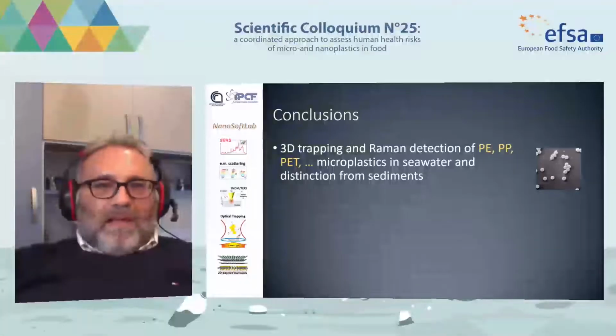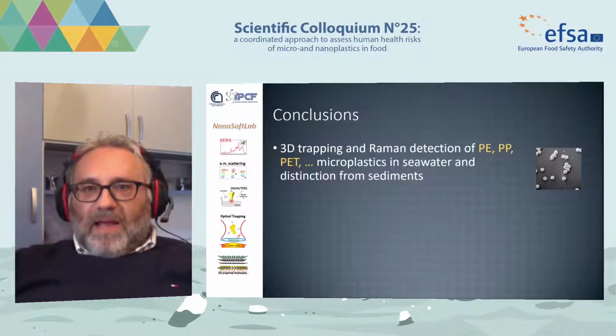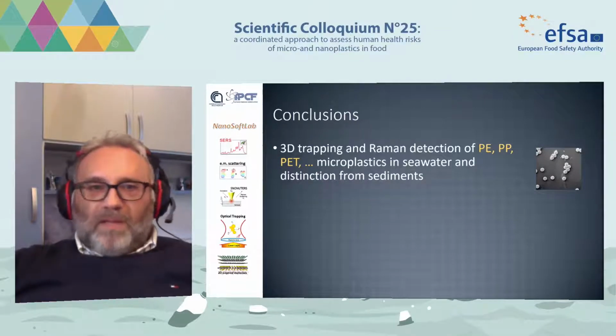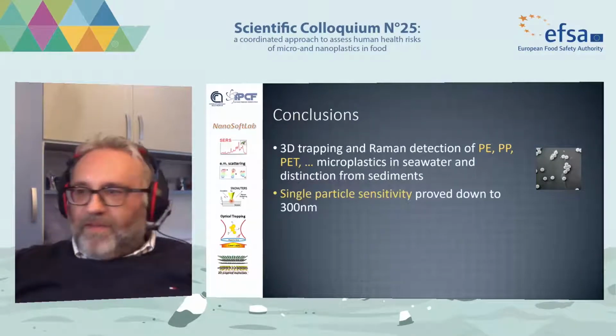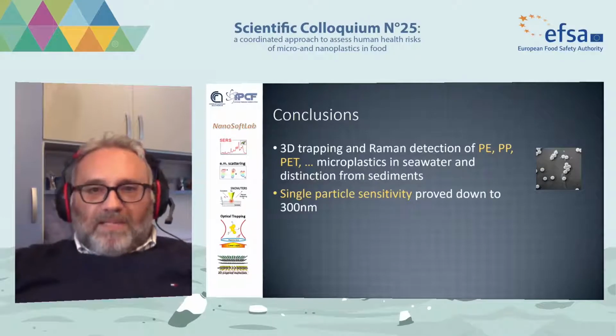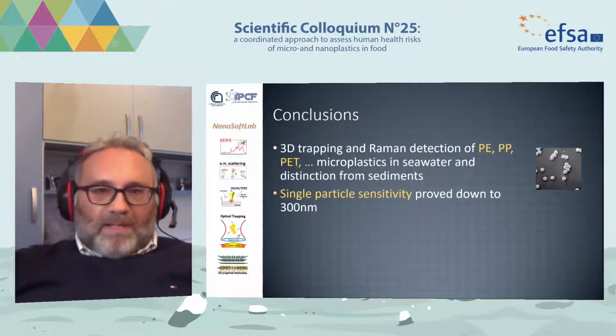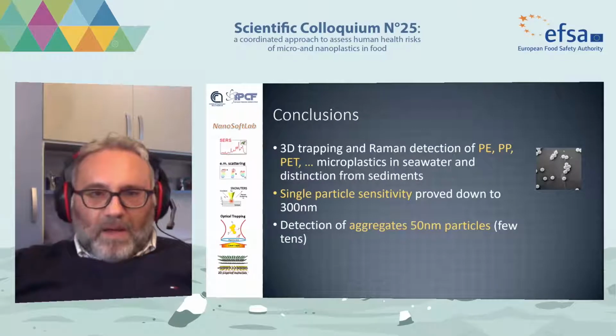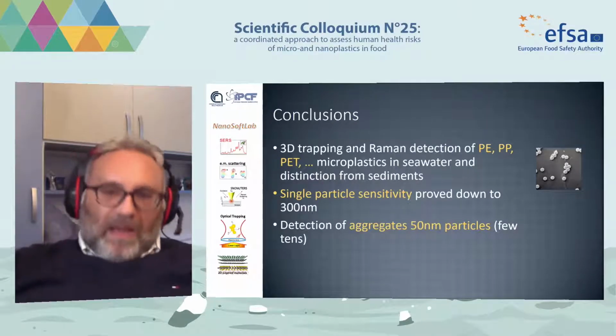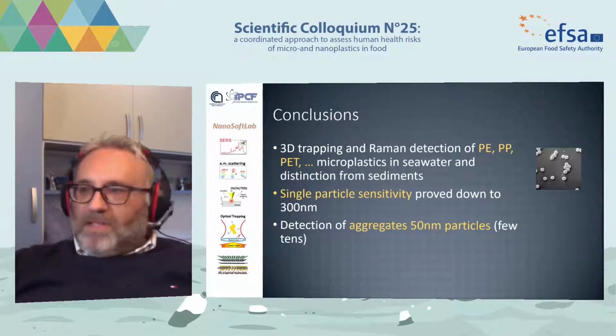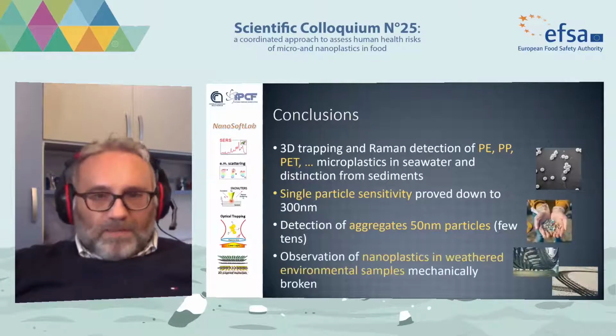We have shown that with optical tweezers, we can analyze polyethylene, polypropylene, PET, microplastics, and nanoplastics of different materials. Single particle sensitivity has been shown experimentally down to 300 nanometers diameter. And detection of aggregates of 50 nanometer particles has been shown, some tens of particles.